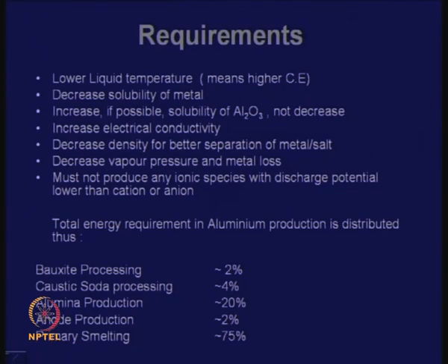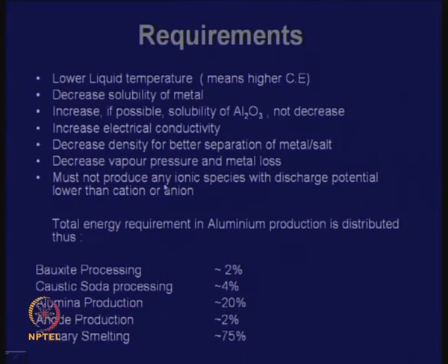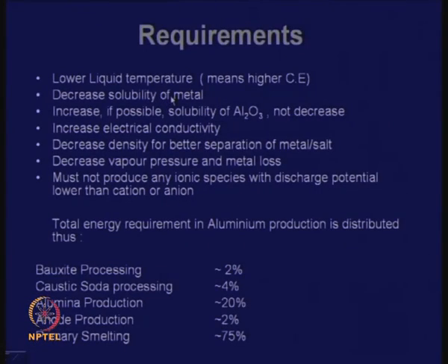Now, there are many requirements that we have to keep in mind in this electrolytic process. We want a lower liquid temperature, which means we have to operate at as low a temperature as possible, because then we will get a higher current efficiency. Otherwise, we will be using current to generate heat. We have to decrease the solubility of the metal in the fused salts. Please remember, I had given some lectures that many metals dissolve in their own salts, and if that happens, then it is a metal loss. That can be decreased by adding other salts. If you recall, if you add third, fourth, fifth salts, then the solubility of the metal in its own salt goes down.